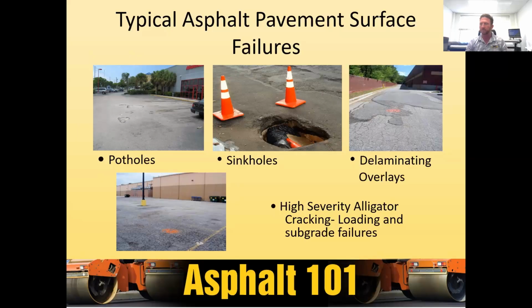And then high severity alligator cracking, loading, these are subgrade failures. If you see native soil or brown spots coming up through the surface of the asphalt, that means that you have a failed surface, you have a contaminated base, and now you've got to do something much more heavy and costly to that pavement than just a mill and overlay. Okay, so when it gets to this position down in the bottom left there, we've got to deal with that much more accordingly.